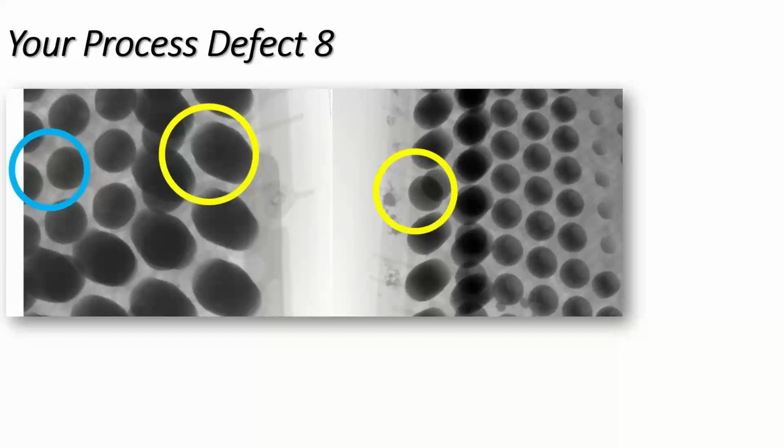And they've soldered beautifully. But if you look at the right-hand side image where I've circled it, you can actually see a ball which is sitting on top of a ball. And it's fairly easy with this X-ray image to see the differentiation between the bottom and the top ball. But if you look at the rest of the rows, the two rows there, you can see you've got effectively column joints. So we've got one open circuit intermittent joint.